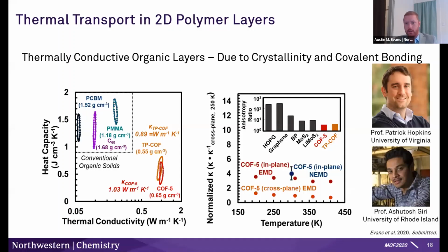And what they found using a combination of time-resolved spectroscopies and molecular dynamic simulations is that COFs are far more thermally conductive than other organic materials. And that largely arises from the fact that they are highly crystalline and covalently linked across extended length scales. So for example, C60 fullerenes are quite thermally conductive for organics because they're very crystalline, but they still fall short of COFs because they're not covalently linked in all dimensions. And also, just as an interesting note, the thermal conductivities are anisotropic as a function of the anisotropic structure.